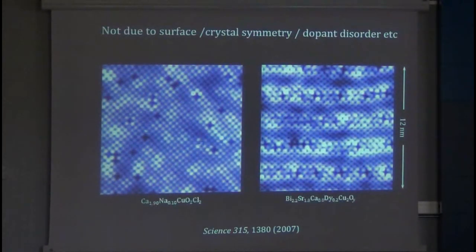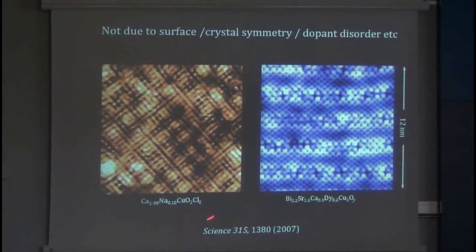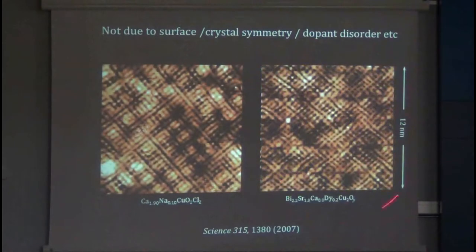We wanted to check that this is not some technical mistake of the tip or the surface or a bad graduate student or the software or anything. So we compare different cuprates at low carrier density where these phenomena are detected. So here's oxychloride and here's BSCCO. And in terms of the breaking of translational and rotational symmetry, the electronic structure of these compounds, which are physically very different, is basically identical. So we're very sure that this is a global property of the cuprate parent underdoped compound.